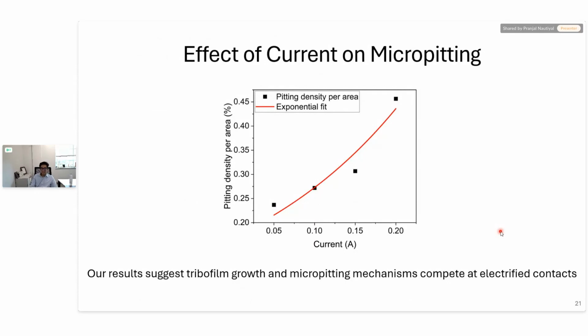So our results suggest that the electric fields promote both tribofilm formation and micropitting. And these two mechanisms, we think, compete with each other, which I think is what leads to a suppressed tribofilm formation at very high currents. Initially, tribochemical reactions are more dominant, and that's why we see an exponential increase in the reaction rate constant. But beyond a critical current, the micropitting wear becomes much more dominant, and that undermines the mechanochemical film formation at these interfaces.